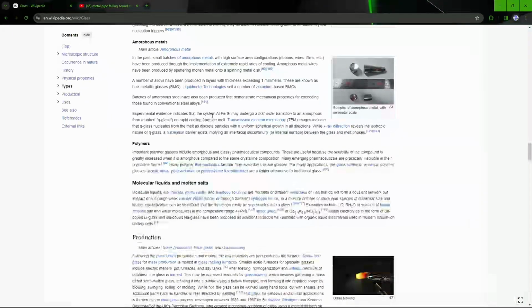Experimental evidence indicates the system may undergo a first-order transition to an amorphous form dubbed Q-glass on rapid cooling from the melt. Transmission electron microscopy images indicate that Q-glass nucleates from the melt as discrete particles with a uniform spherical growth in all directions, while X-ray diffraction reveals the isotropic nature of Q-glass. A nucleation barrier exists, implying an interfacial discontinuity or internal surface between the glass and melt phases.